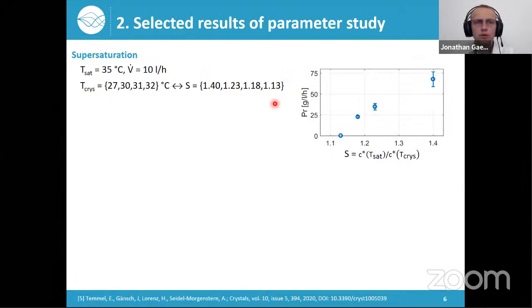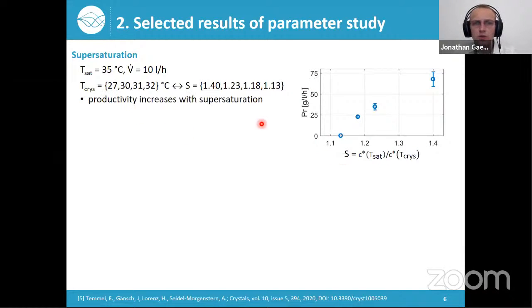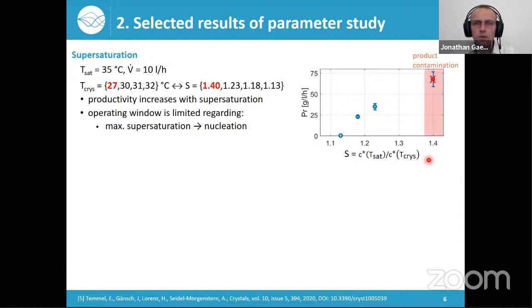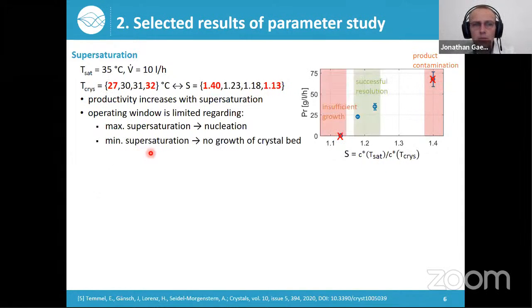Now I would like to show some selected results of the parameter study which we performed. First, regarding the supersaturation. Here are productivities for 4 different supersaturations. What we can observe is first that the productivity increased with the supersaturation, as expected. But what we could further observe is that our operating window is limited by a certain maximum supersaturation, where the counter enantiomer starts to nucleate and contaminate our product. Further, our operating window is also limited by a certain minimal supersaturation, where our crystal bed stops growing, and as a consequence, our productivity becomes 0.